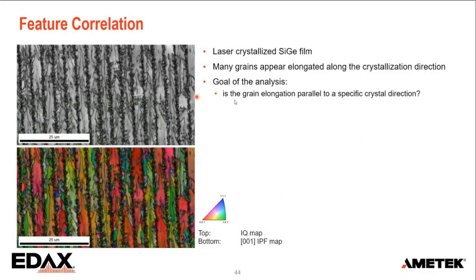Now, here's another example of a feature correlation. It's a recrystallized film, and here I can look at elongation of grains. And what I would like to know here is the elongation of these grains parallel to a specific crystal direction. So is the crystallization going along a preferred direction or not? So this is a normal IPF map. That's the crystal direction sticking out of the sample towards us. So that doesn't show us any information about the elongation of those grains.